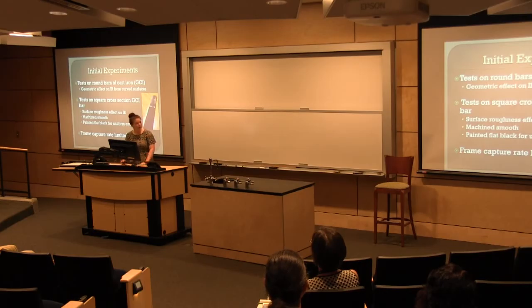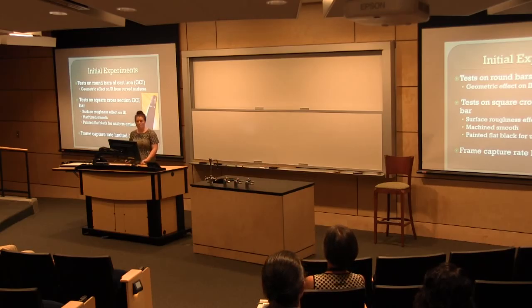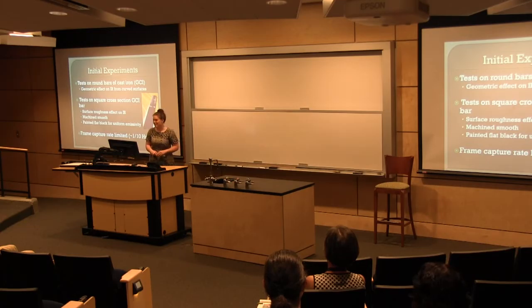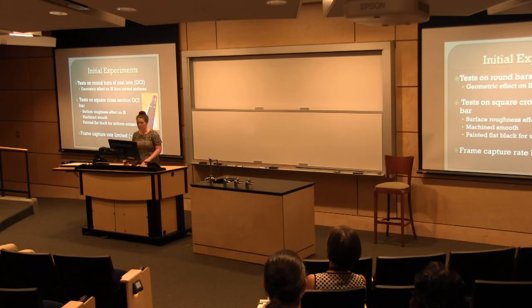So then we moved on to square cross-section, still remaining with the gray cast iron bars. We also saw a little bit of a problem in this. So when we were looking at the images, the graphs weren't very smooth. They were a little bumpy in terms of emissivity. So Dr. Kranoff helped us here to machine the bars to make them extremely smooth, and then we painted them flat black for emissivity purposes to make sure that was uniform throughout to help with our measurements.